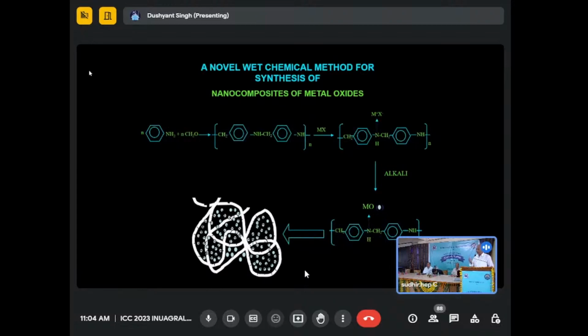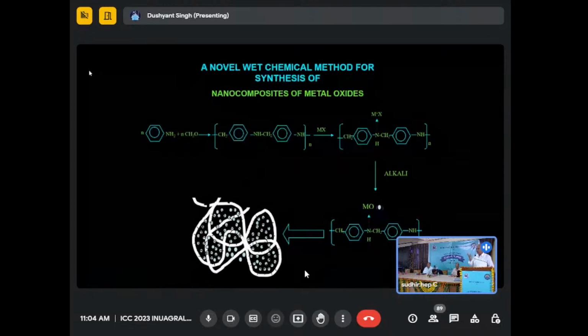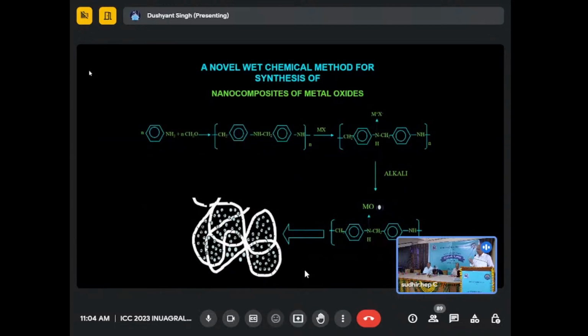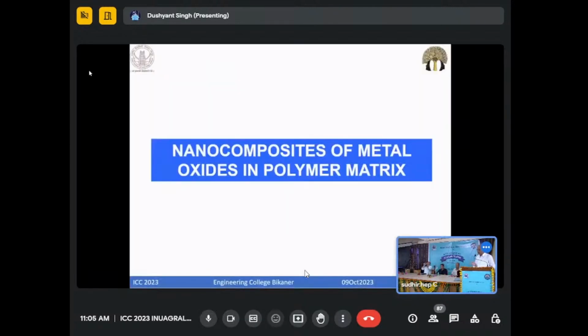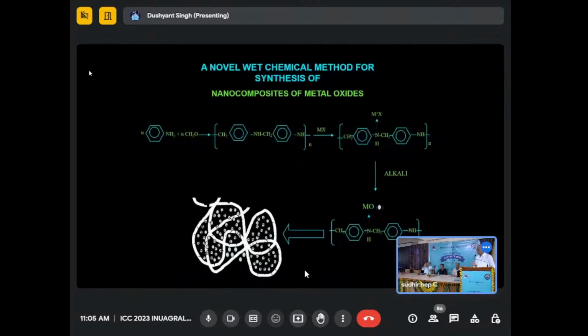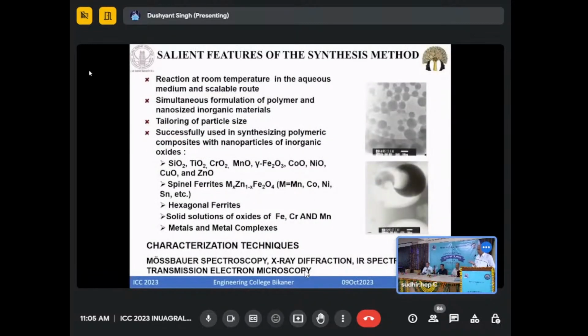I took that material and we took an XRD spectrum, and then broad lines were there. I was not really aware of XRD also at that time. But Dr. Sharma mentioned that broad lines indicate small size particles. And based on that line width, we calculated the particle size to be 50 nanometer. So that was an accidental discovery of making nanoparticles, nano composite material. And this material we made in kilograms. So 5 kg batch scale we made this material.